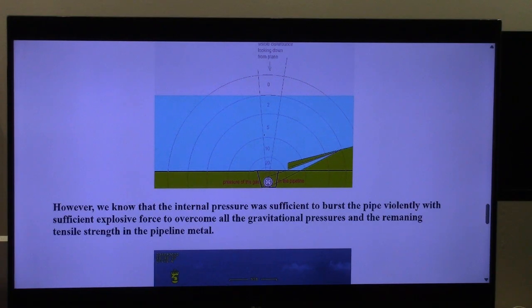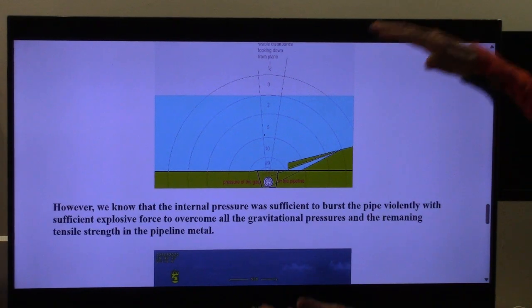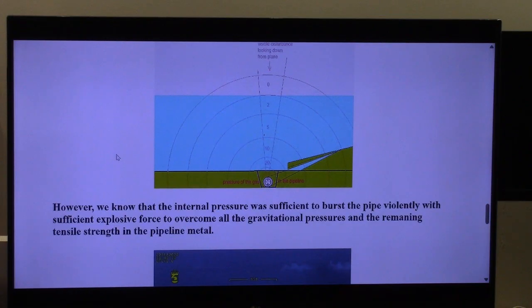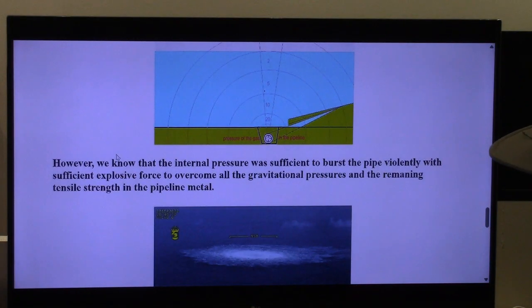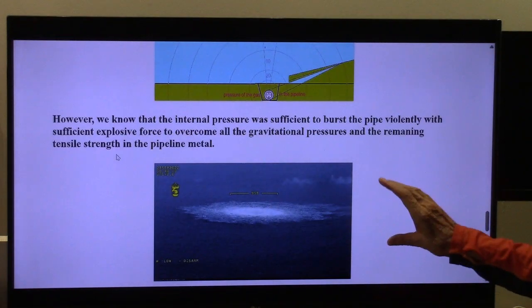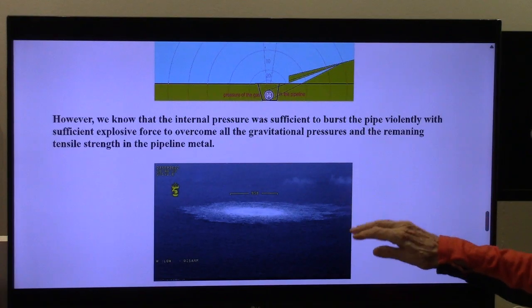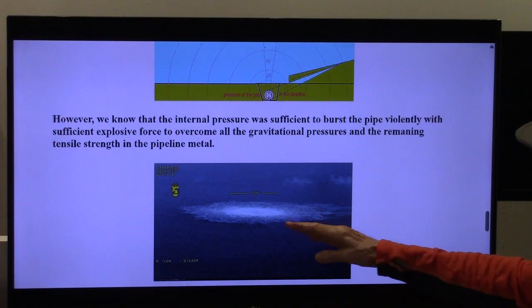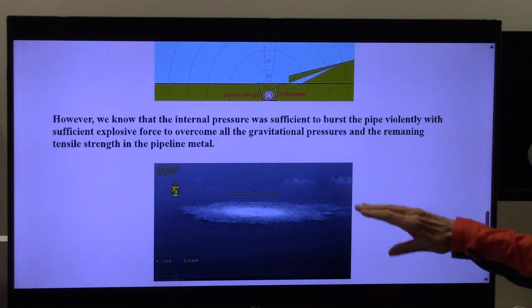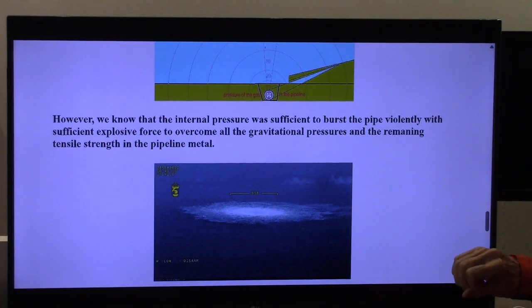However, we know that the internal pressure was sufficient to burst the pipe violently, with sufficient explosive force to overcome all the gravitational pressures and the remaining tensile strength in the pipeline metal. This is shown by the results which were photographed of the gas escaping from the pipeline and reaching the sea surface, where only atmospheric pressure was opposing the pressure of the gas coming from the sea.